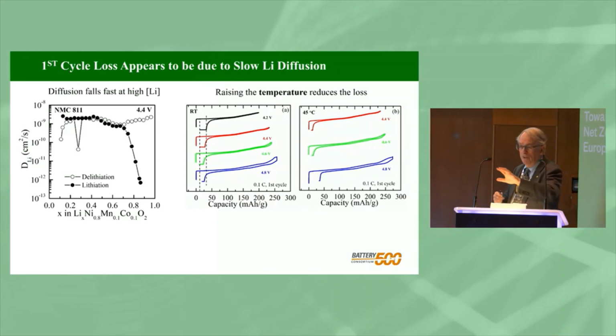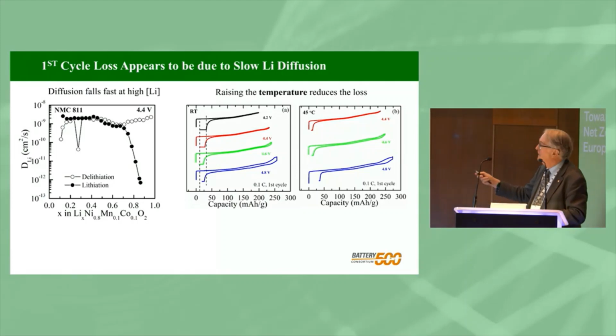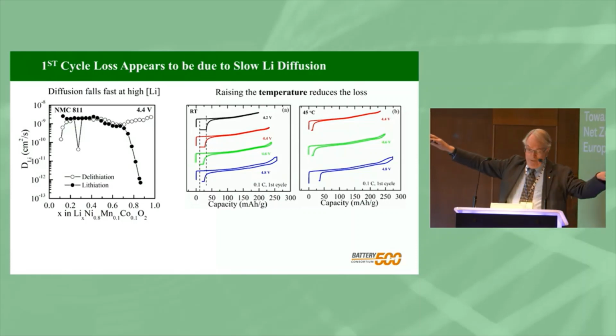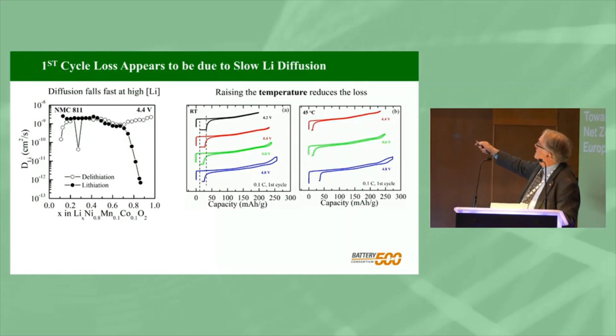And you can look in this audience. The easiest way is to look at a conference room. If somebody comes in now, there's probably an empty seat somewhere in the middle. So everybody has to move to let that person in. It's the same issue with these cells. Taking the lithium out, there's no problem. So this, like emptying electrolyte, it will all flow out. So fast charging is feasible with these materials, but we can't get this in. If this is really kinetic controlled, and if we raise the temperature, then it should get better.